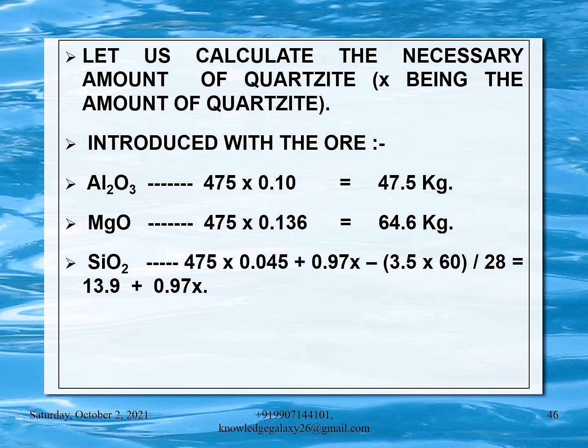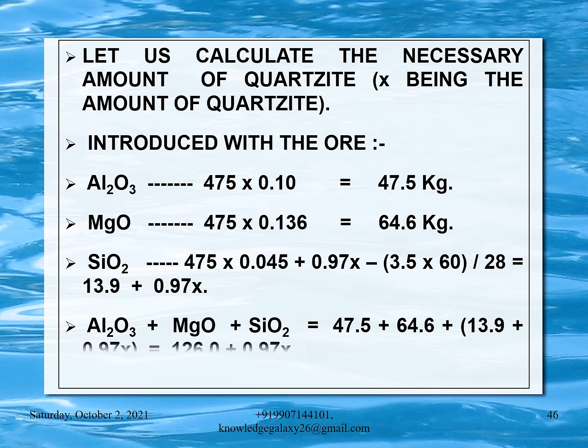So it comes Al2O3 plus MgO plus SiO2 is equal to 47.5 plus 64.6 plus 13.9 plus 0.97x is equal to 126.0 plus 0.97x. 13.9 plus 0.97x is equal to 0.3 into 126.0 plus 0.97x. Here 0.3 is 30% of SiO2 in the slag. Do remember that? Please don't get confused.